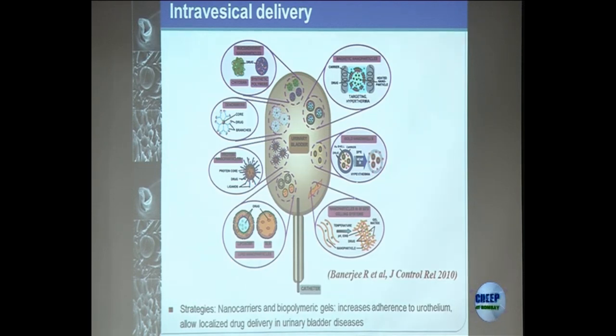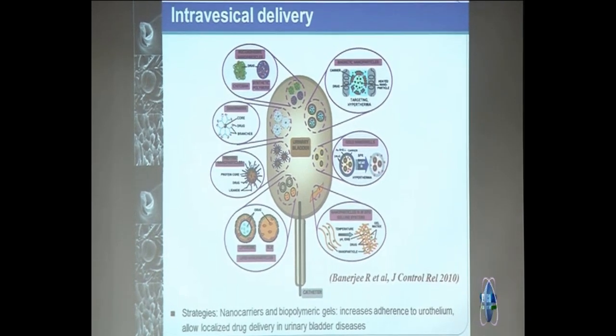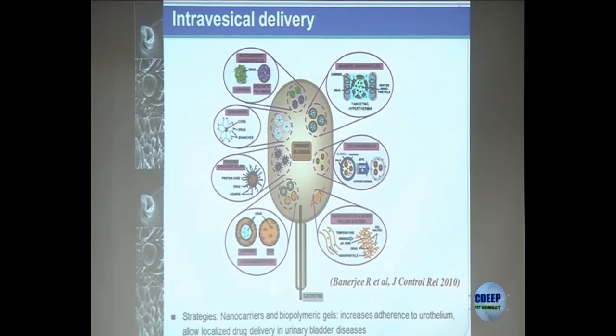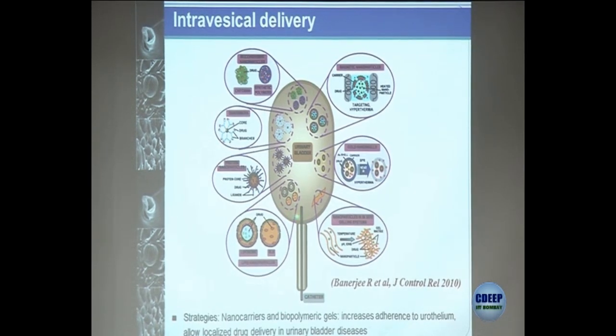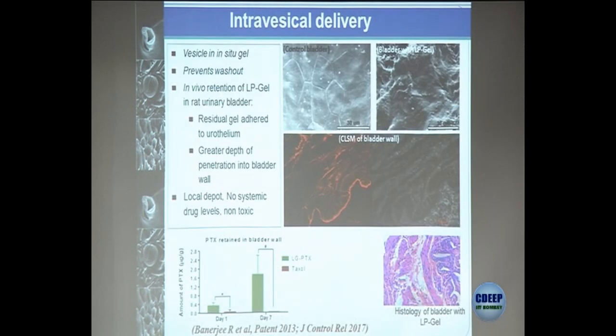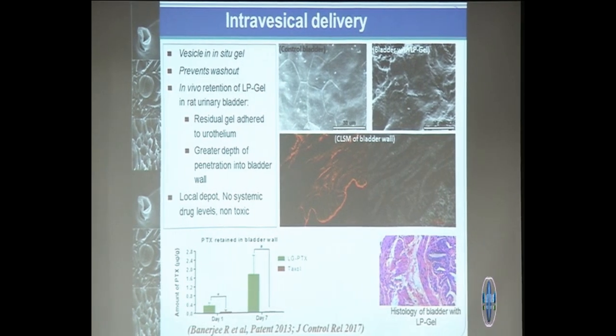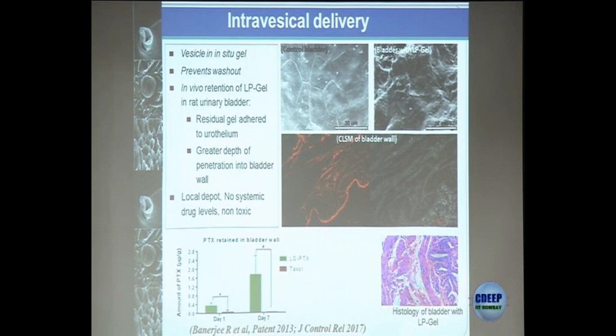So one of the main applications here is in the urinary bladder. Again, a disease of the elderly where bladder control becomes a problem. No drugs reach into the bladder. And if you just instill the drug by a catheter into the bladder, the residence time is 2 hours because of urination. So we are able to make these nanoparticle in situ gels which will coat the inner surface of the bladder and then enhance the retention of the drug. So in this case, as opposed to 2 hours, we can have the drug levels over a week or 2 weeks within the bladder without causing systemic toxicity.